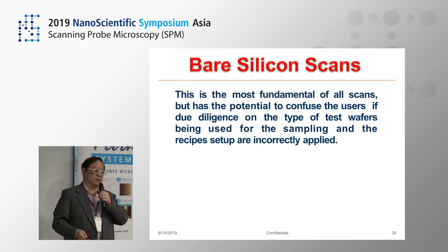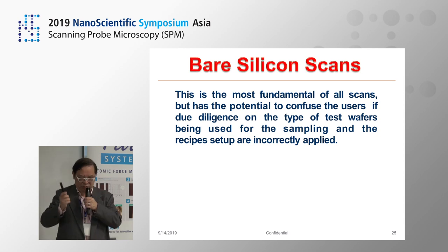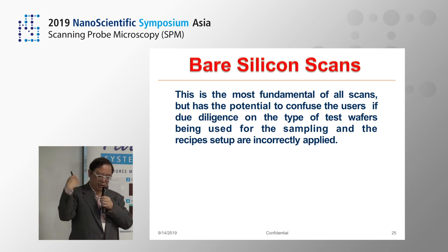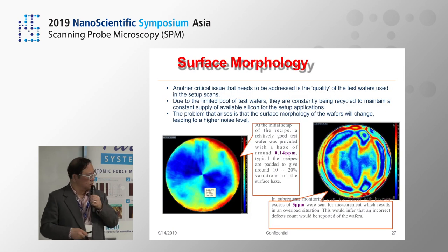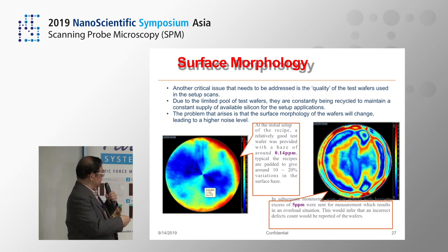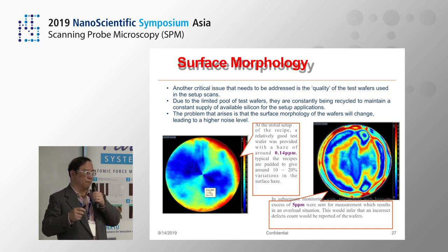Then we come back to bare silicon. Bare silicon wafers are typically used for test wafers. People ask: how many times can I reuse a bare wafer before I discard it or send it for recycling? Most of the time we just wash it off and assume it's a fresh wafer that can continue. When you scan in the defector it comes back clear — you think no defects means the wafer is good, but that's not truly the case. What I'm showing here is what we call the noise level of the wafers. Over time, with usage, the surface condition changes — what we call the haze setting of the wafers changes, meaning there is defectivity at a more macroscopic level rather than just a particle on the wafer.